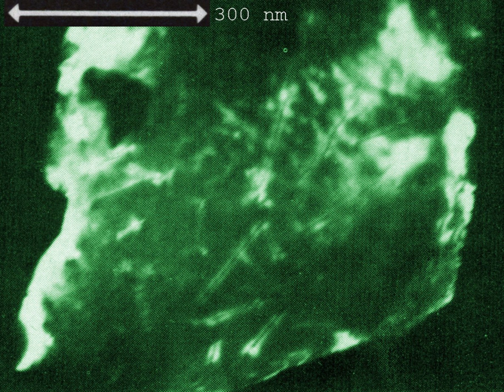generation of elongated structures with a resolution limit down to 8 nanometers, direct generation of holes in thin films without any development process, defining structural depth by ion range rather than by target thickness, generating structures with aspect ratio (depth divided by width) up to 10^4.